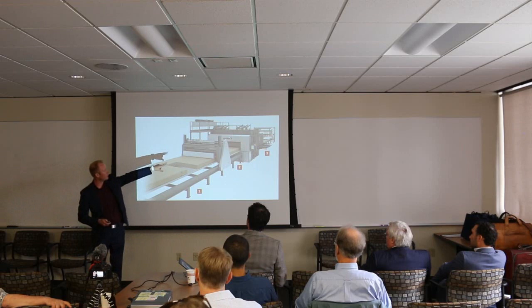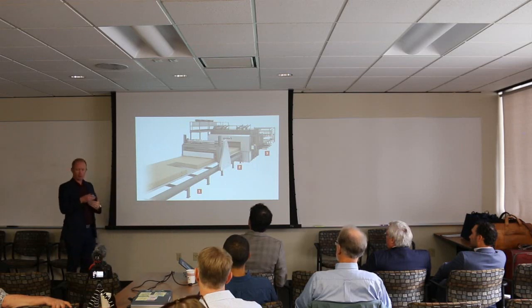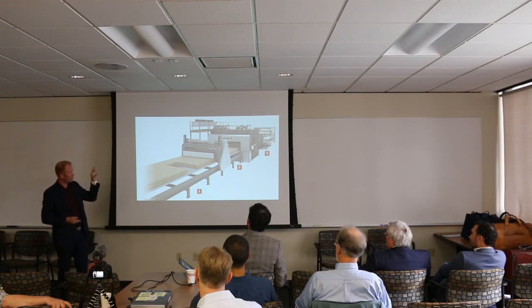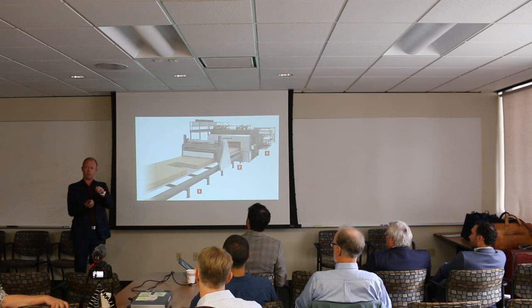So there's the press there. So it's about every 12 feet, and it goes in there and sits in there anywhere from a minute to 3 minutes. It's essentially extruded, so it's a very linear process. But the company that's developed it has figured out how to identify where the voids are to keep from pushing the platens against one another and then bending the plates.